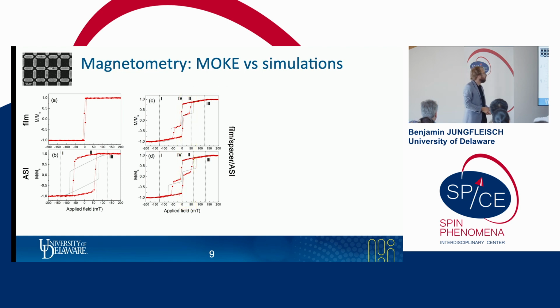We can also take a look at the switching fields for the two different spacer layers. So the top here shows the 2 nanometer spacer layer, the bottom shows the 10 nanometer spacer layer, and we can see that the thinner spacer layer features a smaller switching field. I'm showing here 53 and 60 millitesla. This is experimental data. The corresponding results from the simulations are shown in parentheses. So how do we understand this difference in the switching field?